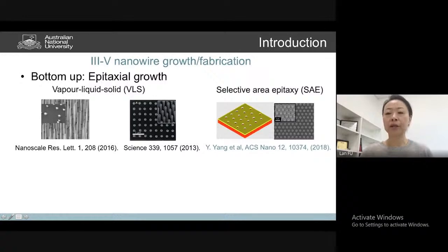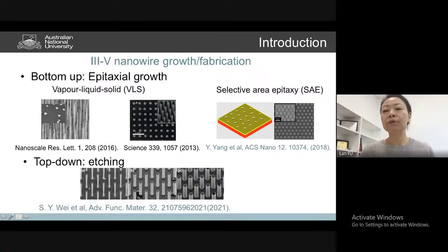So this way you avoid incorporation or use of the metal nanoparticles. There's also the reverse way, the top-down etching. With that, you don't need an MOCVD reactor, which is actually quite an expensive piece of equipment, millions of dollars. You can use a simple ICP, inductively coupled plasma, etching technique to etch nanowires.